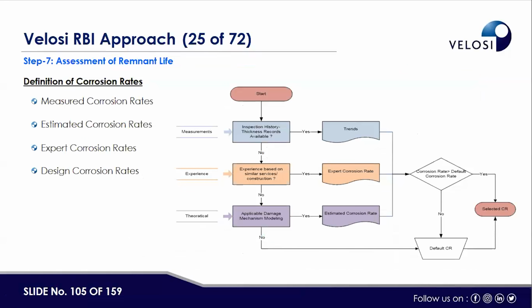Then, assessment of remnant life as a part of the review: we have four kinds of damage or corrosion rates. One is the measured corrosion rate, then estimated corrosion rates, expert corrosion rates, design corrosion rates, and measured experience theoretical. Based on that, we have a trend, an expert corrosion rate, and an estimated corrosion rate based on the available corrosion allowance and remnant life. We select the corrosion rate that is available, and preferably it should be the measured one. The second is the expert one, the third could be the estimated one, which is mostly conservative, and then we set the default or whatever corrosion rate is available, and then we estimate the remnant life based on the available future corrosion allowance.